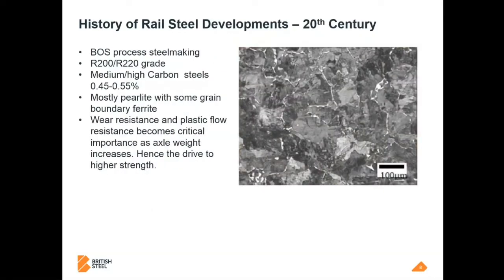Into the 20th century then, we start to see Bessemer-successor basic oxygen process steelmaking, particularly in Europe, taking over as the preferred method for rail steel manufacture. And obviously with that process, you get a further improvement in steel cleanliness, in your composition control, and you're able to go even higher on the carbon scale. The trouble is as you get to higher carbon levels, hydrogen starts to become more of a problem for shatter cracking and delayed hydrogen cracking.